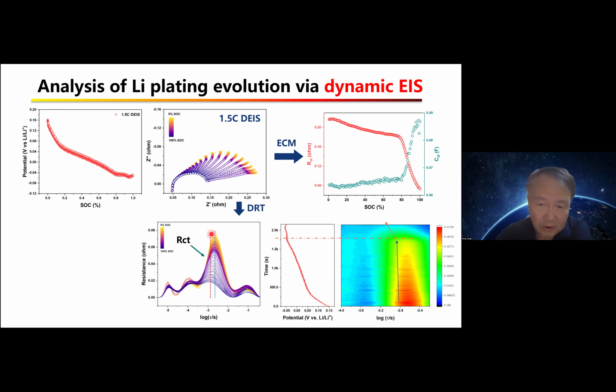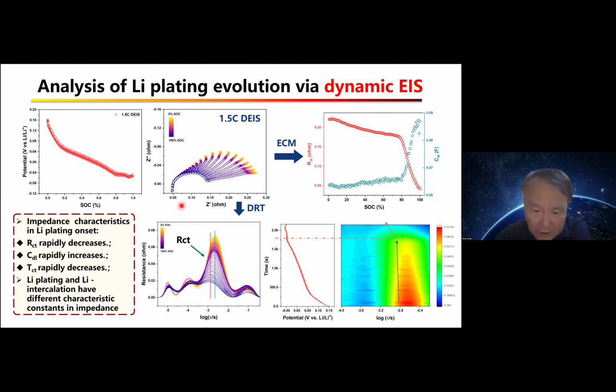During the charging process, we can see that the reaction times also change, especially for some charge transfer reactions. The time constant of the charge transfer process decreases during the charging process.